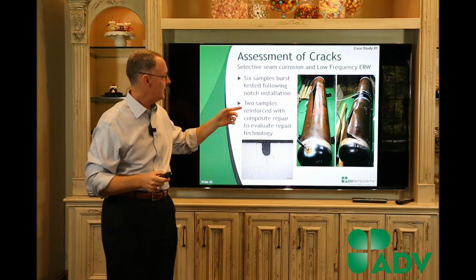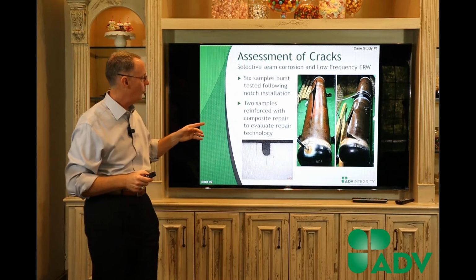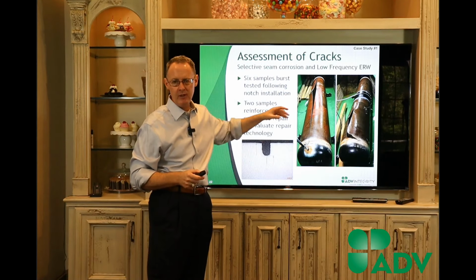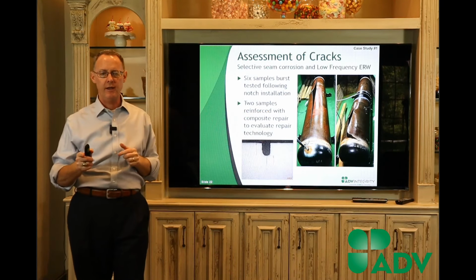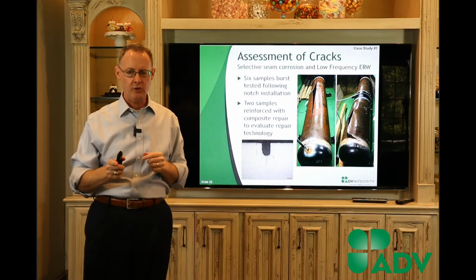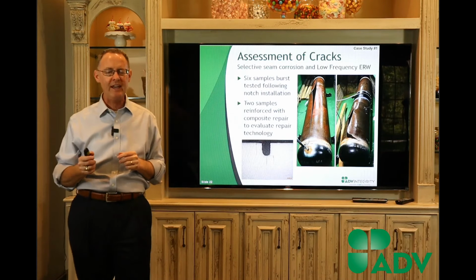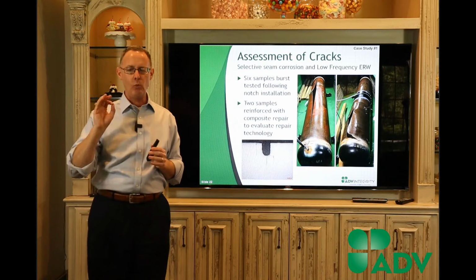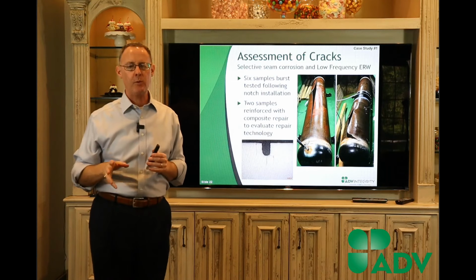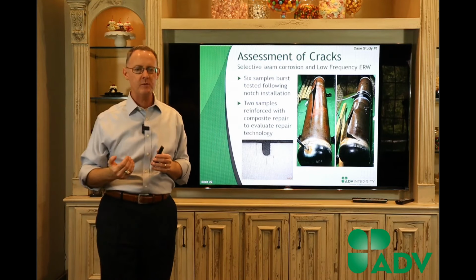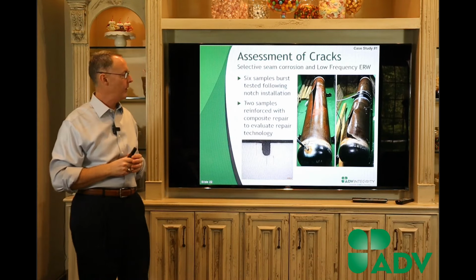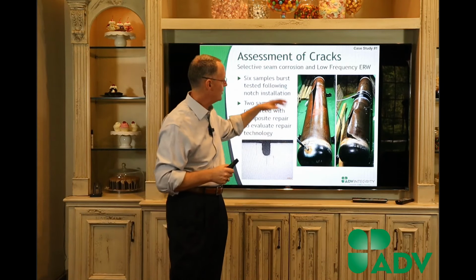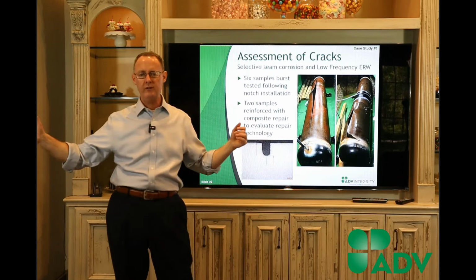And so what you can see in these samples here, there's a couple things. One is the left image, you can see the fracture. And if I show this picture to you, and you've been in the pipeline industry any length of time, and I said, why do you think it fell that way? Your response would be, because it's in a low frequency ERW seam. And that's exactly what happened. So we had a notch, we pressurized it, and it ran the whole length of the pipe.